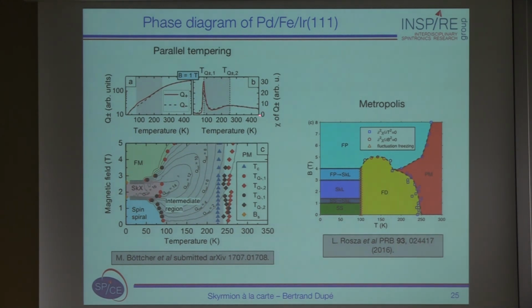And this quantity, if you record the position of the two peaks, you can define the transition region between all the different phases with, let's say, a nice precision. So here you have the pocket of the spin spiral. You see that now the TC is not constant if you compare with this phase diagram already published. You see that the TC, when you have a spin spiral ground state, decreases as a function of magnetic field. You have here the pocket of the skyrmion lattice. And then this critical temperature increases again when you are in the ferromagnetic state.